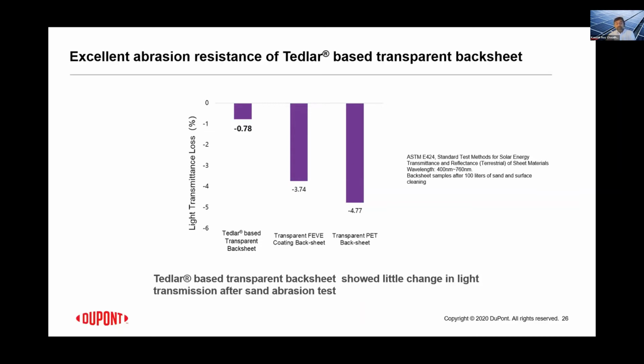So this again gives us confidence that there's very little change in light transmittance after this test, and therefore in real life situations in deployment in even dusty and sandy areas, the product should be pretty good in terms of its reliability. And by the way, as I mentioned, the sand abrasion test is a rather harsh test, which is much harsher than what the modules actually see in deployment.